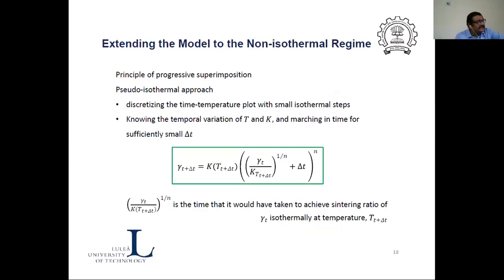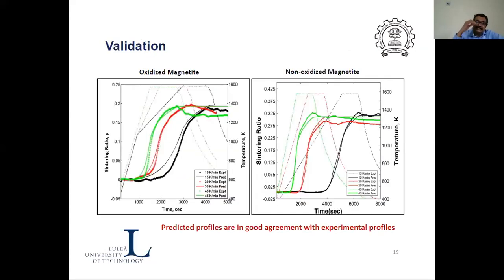And then we expanded this model, because all the studies were conducted in isothermal conditions. So we expanded the model to non-isothermal conditions. Of course, these involve some techniques of modeling, but these are not very difficult things. These are used in many other places. For example, for grain growth on the runout table, if you want to predict the microstructure, there are equations available. So along the same line, we developed the model, and we conducted non-isothermal experiments to see how well our predictions match the experiments.